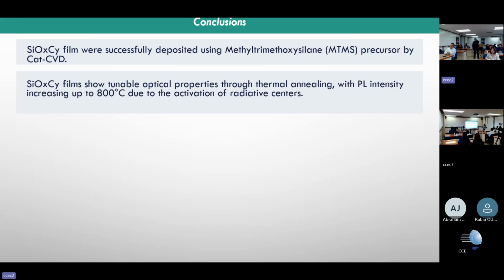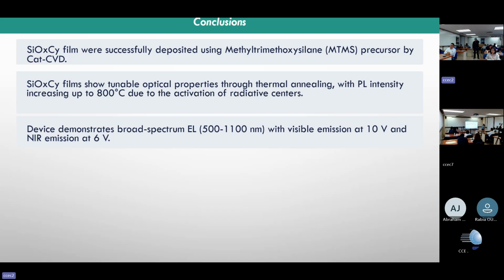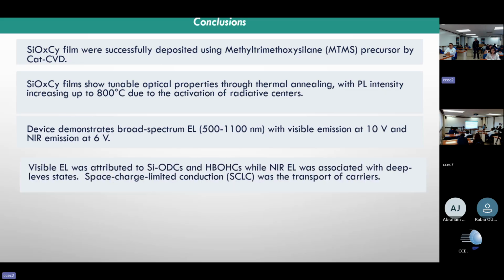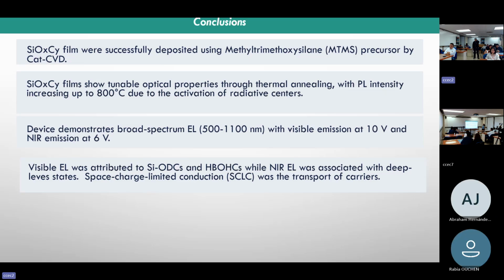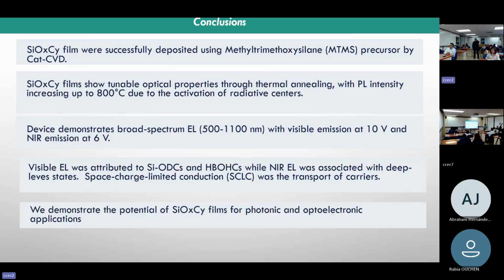Oxycarbide films showed optical properties; the photoluminescent intensity increases at 800 degrees due to activation of radiative centers. The device demonstrates a broad spectrum, visible and near infrared emission. The visible electroluminescence was attributed to silicon oxide deficient centers and neutral oxygen hole centers, whereas near infrared electroluminescence was associated with deep level states, and space charge limited conduction was the transport of the carriers. We demonstrate the potential of oxycarbide silicon films for photonics and optoelectronics applications.